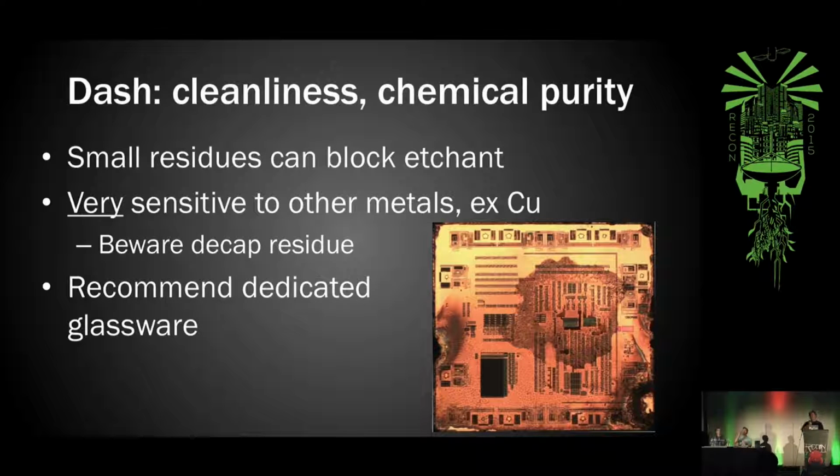So the next issue that you run into is that things need to be very high purity. I think this is one of the issues I ran into using the early hardware store chemicals: they had different additives in there that were causing interference. The picture to the right, for example, shows interference. Those little circles on the left and the right, I believe, are from tweezers that grabbed the die, and they deposited a very small amount of residue onto the die, and that was enough to completely ruin the reaction on the die and cause lots of problems.